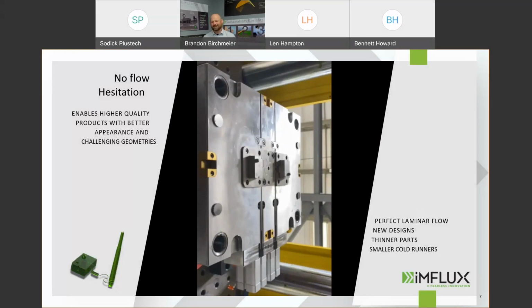We built this on purpose because you can't mold this traditionally. As soon as you hit that very small gate section, gate thread, your part wants to flash, right? Because what are you doing? You're telling your machine how it needs to operate, strictly from the machine standpoint, with little regard to what's happening in the plastic. So if you tell that injection molding machine to inject that 2 inches a second, it'll do that, but you're going to flash that small runner.